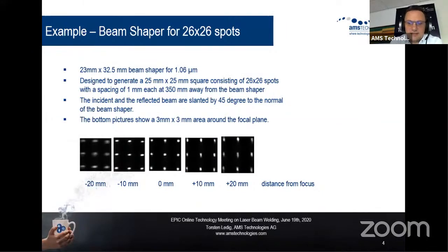So here on this slide, you see one example, a beam shaper, which generates 26 by 26 spots. The beam shaper has a size itself of 23 by 32.5 millimeter. It is used to generate a designated 25 by 25 square millimeter square, consisting of 26 by 26 spots with a 1 millimeter spacing between each of the spots, at a distance of 350 millimeters. So you see here the beam quality in the focus, in the focal plane, and in front and behind the focal plane.